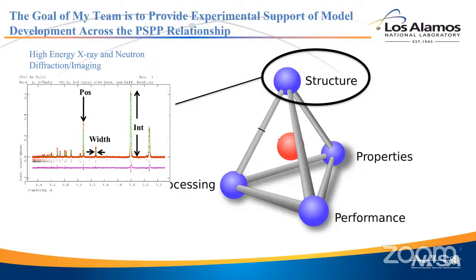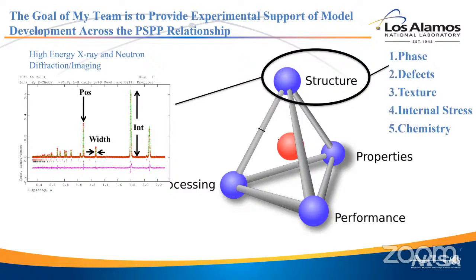But we take all of that, and this is one of the things I'll kind of preach on a little bit today. Parameters for diffraction patterns are meaningless, right? Telling somebody that a peak has a certain intensity doesn't mean anything for material scientists. What matters are microstructural features. So we want to be able to pull out things quantitatively with uncertainties, like phase, defect concentration, dislocation densities, texture, internal stresses, solute chemistry. These are all things that, if you're careful and you do the measurement right, you can get out of the diffraction pattern. And that's, again, our job.